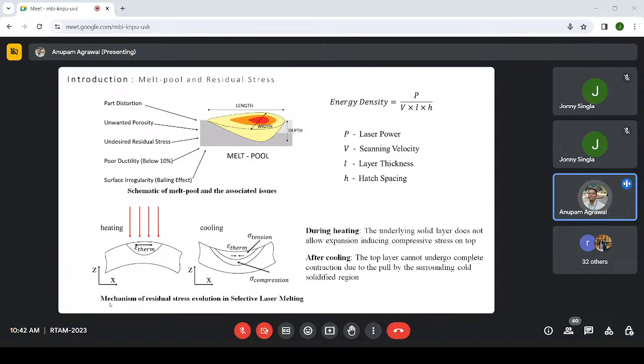Usually the residual stresses get formed because during heating the underlying solid layer does not allow expansion. So while the powder layer is getting heated, the top surface of the powder receives the laser heat and tries to expand. However, the bottom portion of the powder is not heated, because it is a quick process and there is hardly any time for conducting heat throughout this powder layer. So the top portion tries to expand, the bottom portion of the layer tries to contract. So during heating, the underlying solid layer does not allow expansion, which induces compressive stresses.